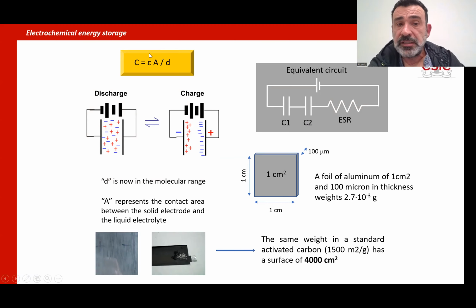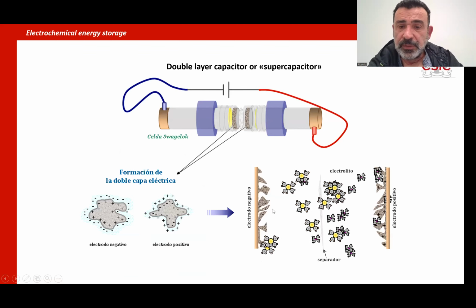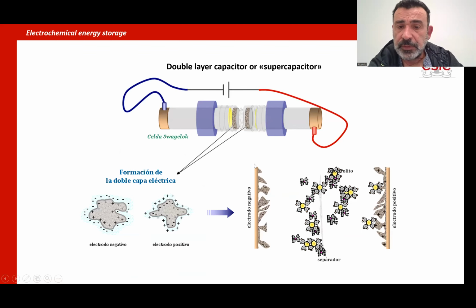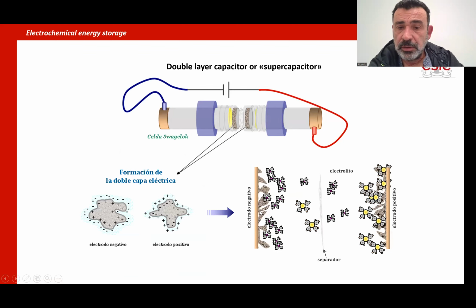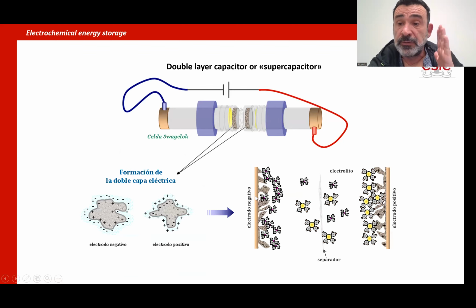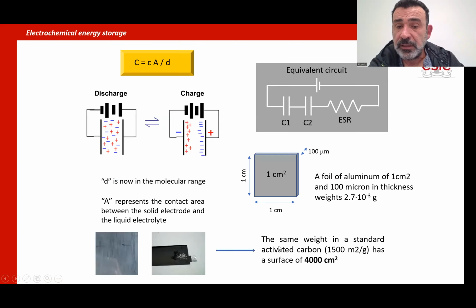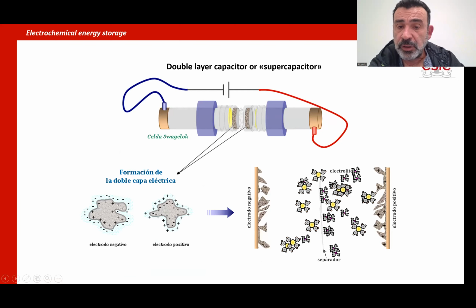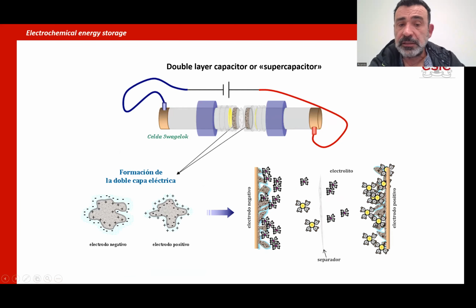Then the changes in A and D are what transform a conventional capacitor into a supercapacitor, increasing the capacitance from microfarads to thousands of farads, okay? Increasing several orders of magnitude. Just going back to this concept, what you make is to transform the electrode, not a smooth surface, but using an activated carbon, you have a high surface area, and then the ions are adsorbing between all this surface area, increasing A.